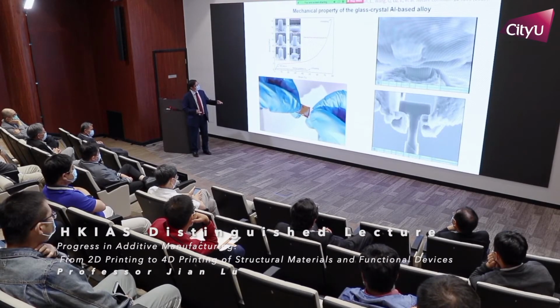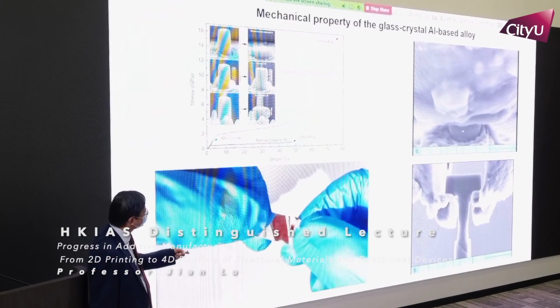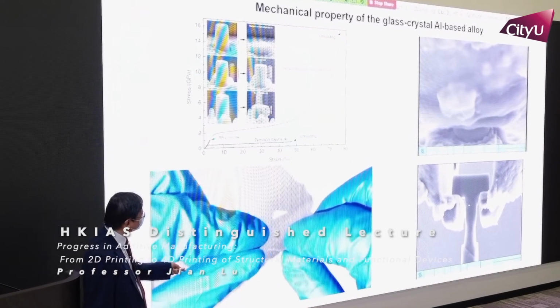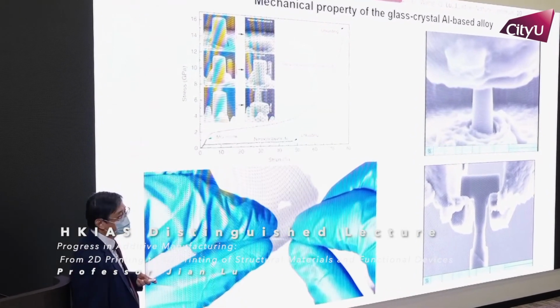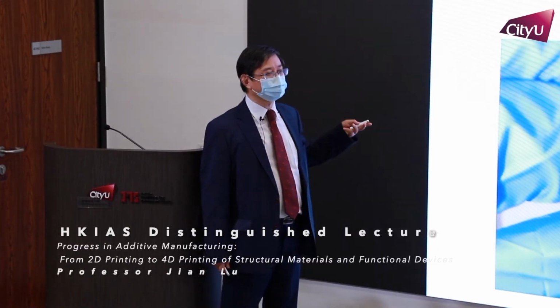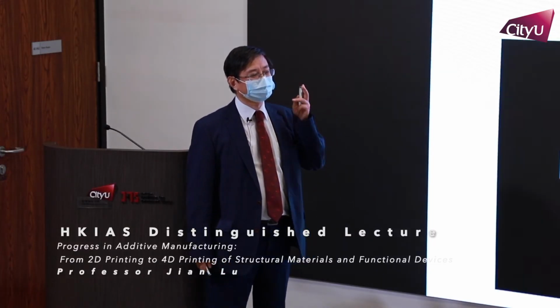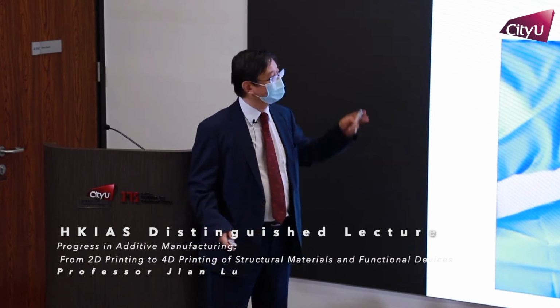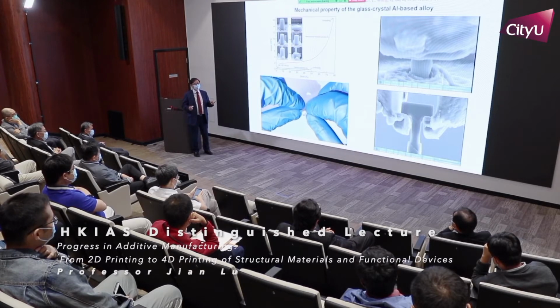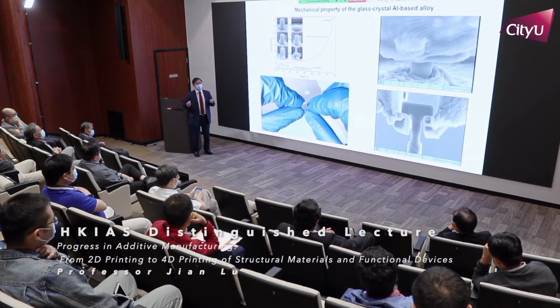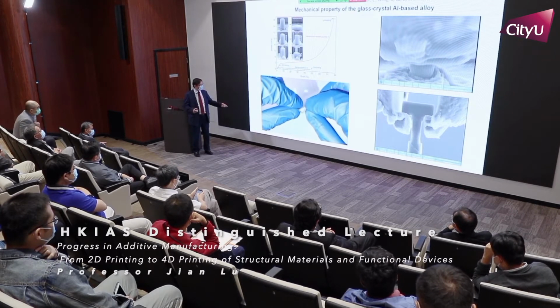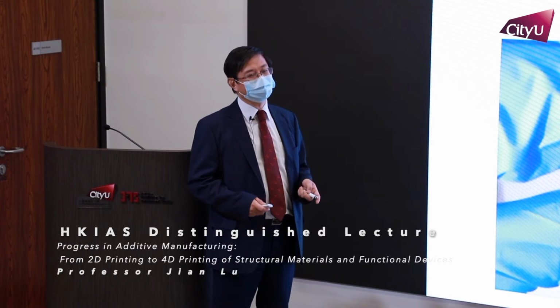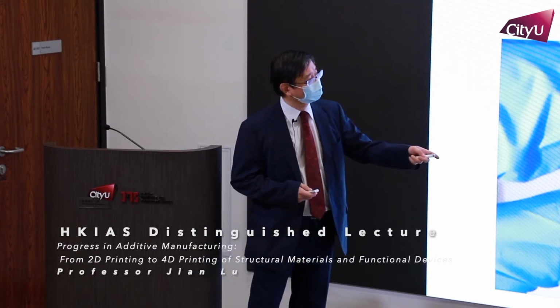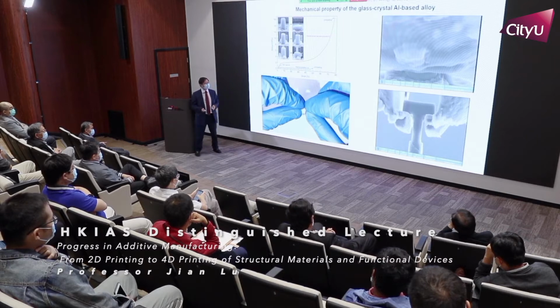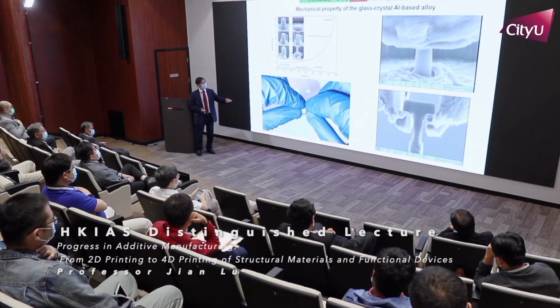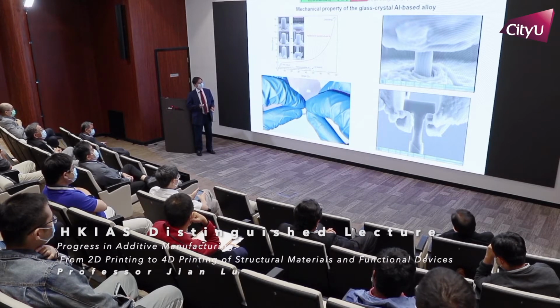So how did that happen? Basically, you can see during the deformation, compression, and tensile test, this material is very ductile. Why? Compared to the previous material, the grain size is smaller than 10 nanometers, so without any dislocation. Here it is 10, 20 nanometers, then the grain has a capacity to deform. For this reason, this material has a very strong strength, but with high deformation capacity. When you do the compression test, we never see a crack. So, a very high deformation capacity.